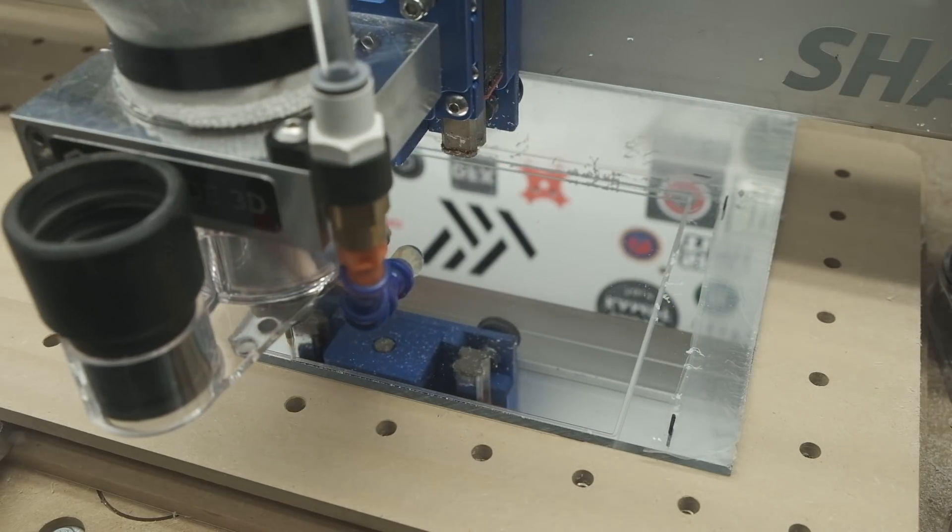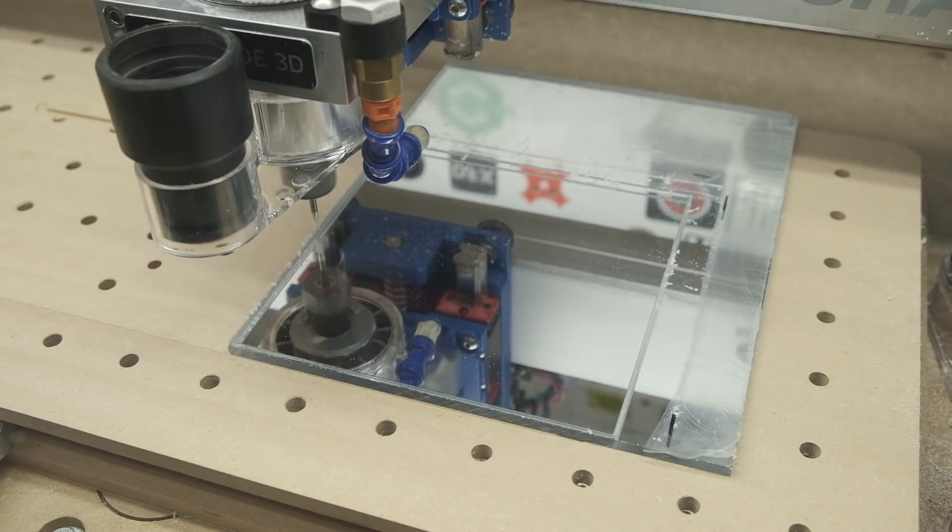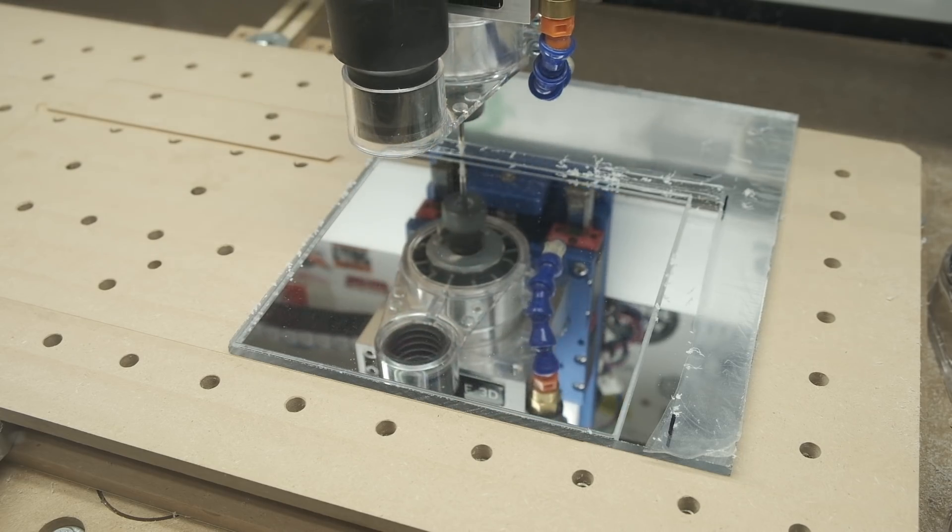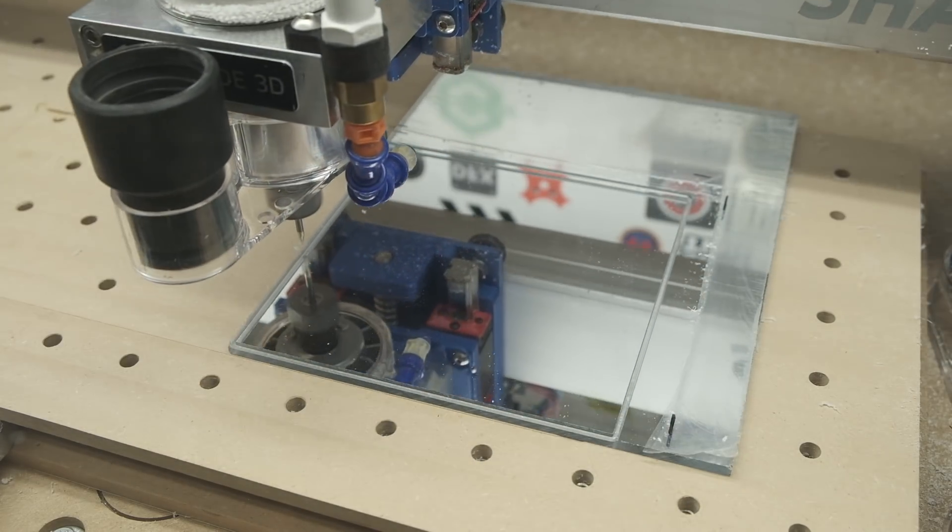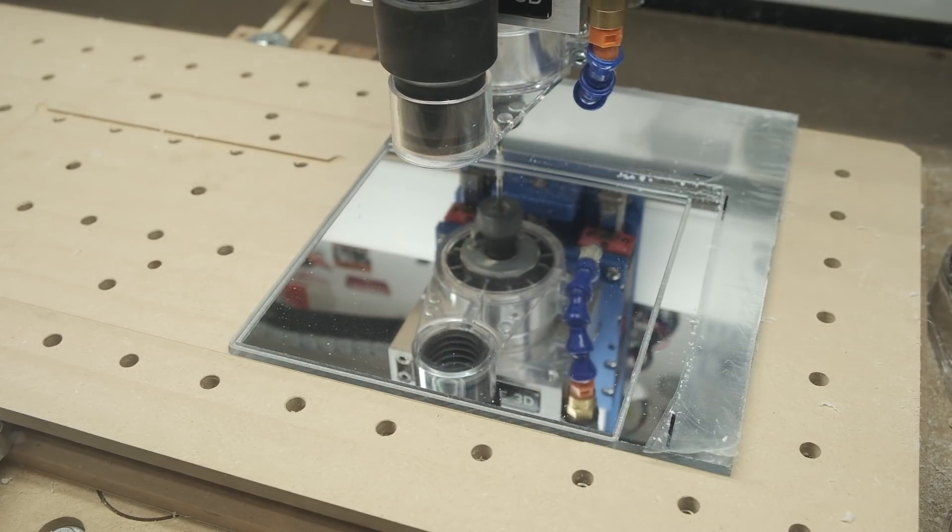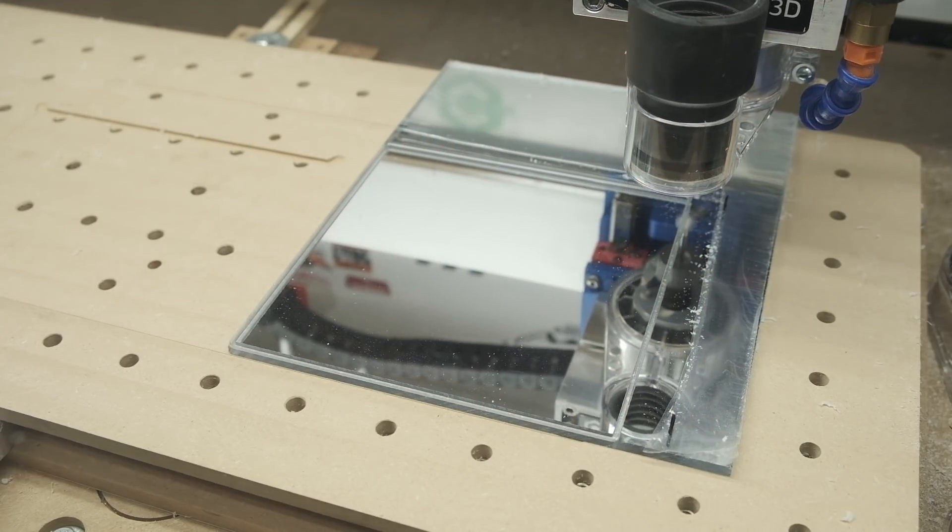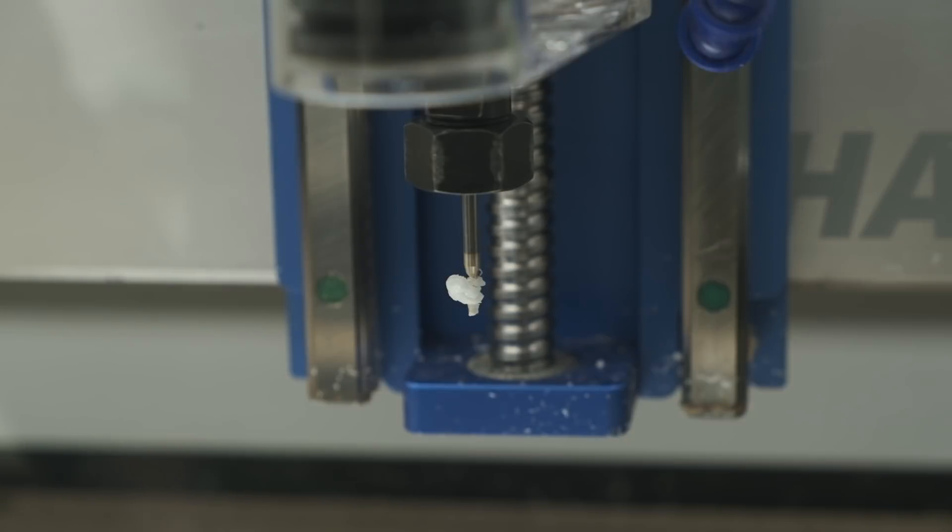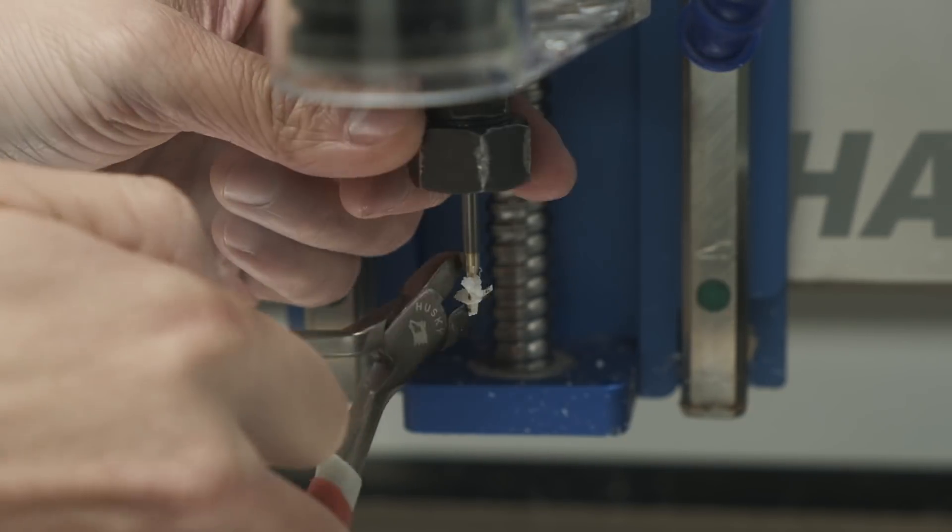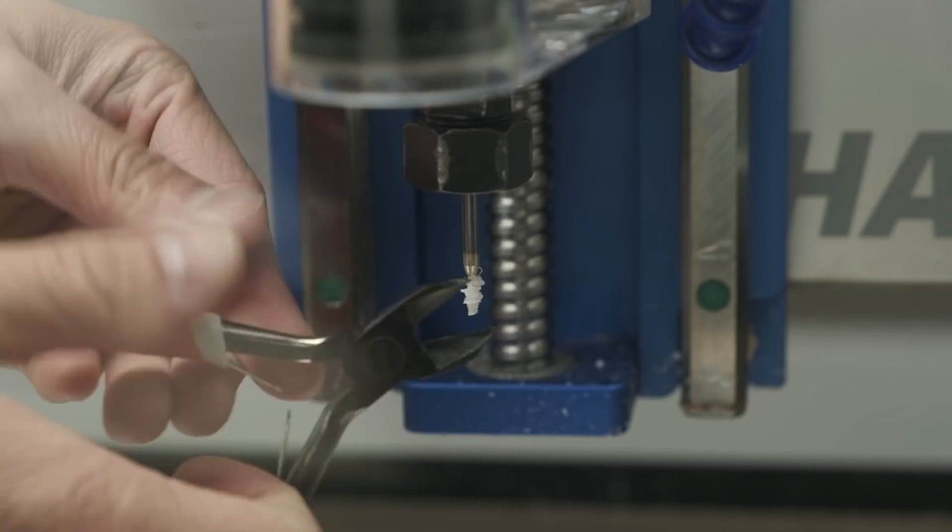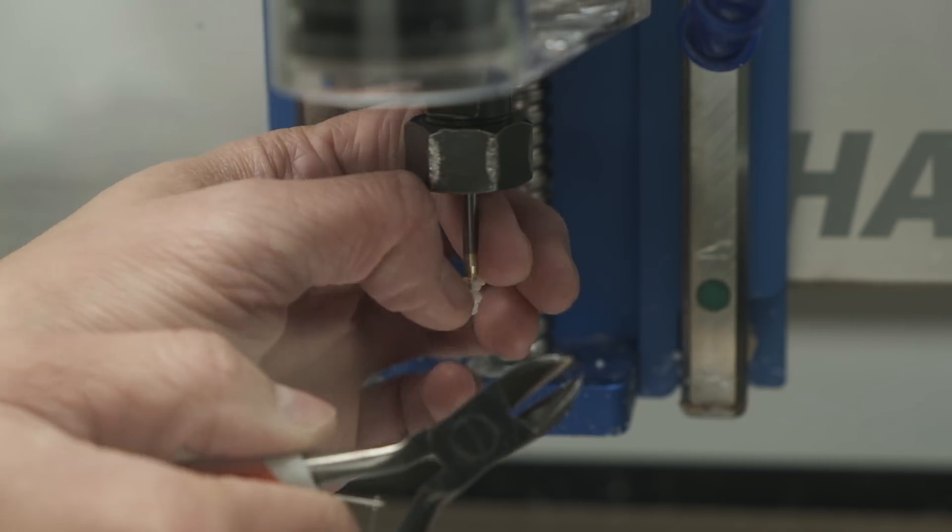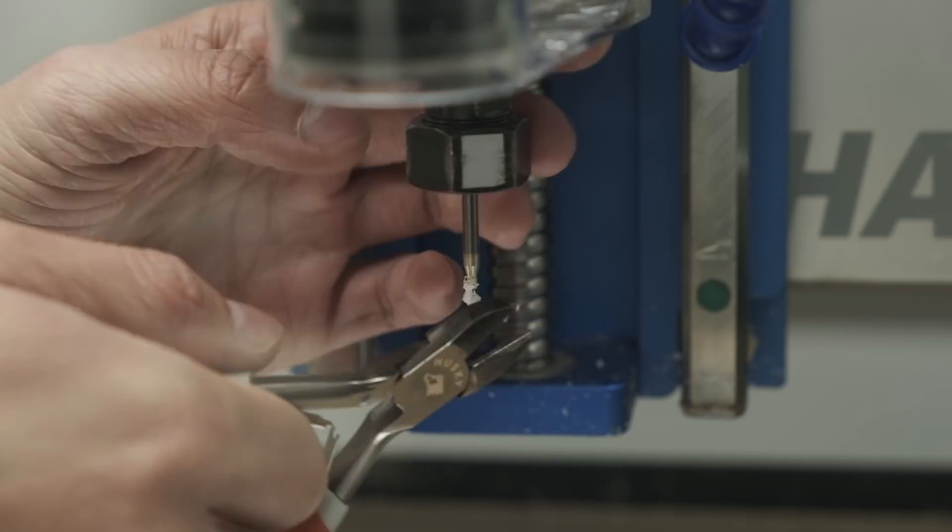Next was the acrylic mirror, and here, things started out well, but as the cut got deeper and deeper, something seemed off. I was getting really fluffy chips that weren't evacuating the cuts well, and as soon as I started to see them clumping up on the end mill, I hit pause. If you let that ball of melted acrylic keep spinning on top of the material, you're going to see and feel a really nasty surface finish around the edges. I used some cutting pliers to gently break off the pieces of acrylic and try and salvage the tool and program.